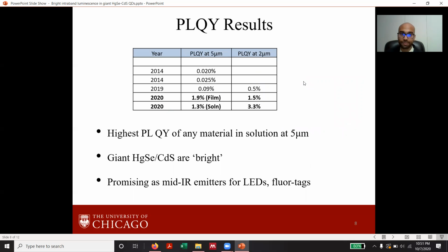By measurement of the doping and the absolute quantum yield, we find that the quantum yield of the giant mercury selenide CdS dots is 1.9% at 5 microns in films and 1.3% in solution. So this is a factor of 20 larger than the previously reported quantum yields at 5 microns, and it is by far the brightest material in solution in the mid-infrared. Though we say that these dots are bright, the quantum yield is still 2%, and there is still a long way to go. But now we are entering a regime where these materials are showing promise for applications as mid-infrared emitters in LEDs and biological fluorescent tags.